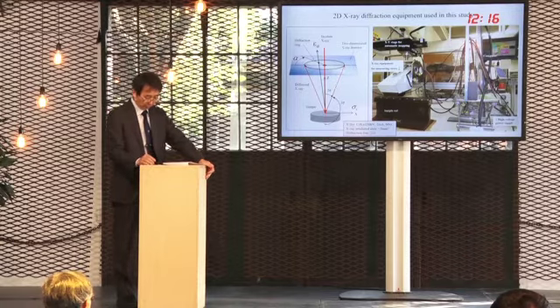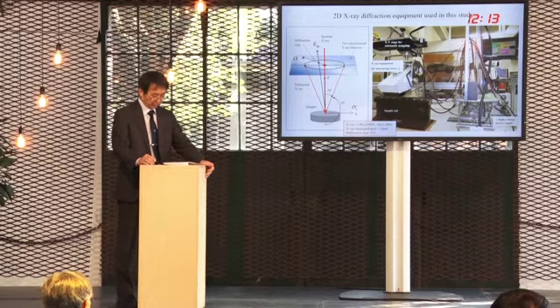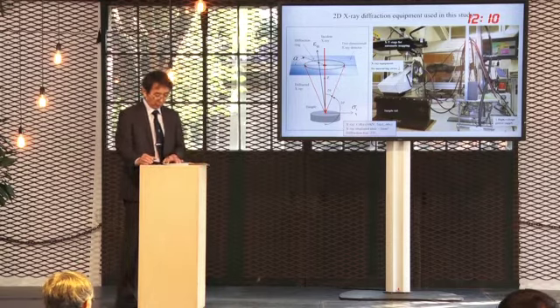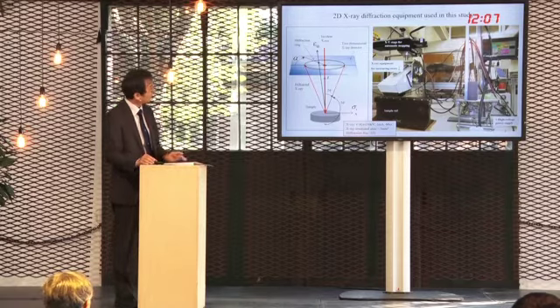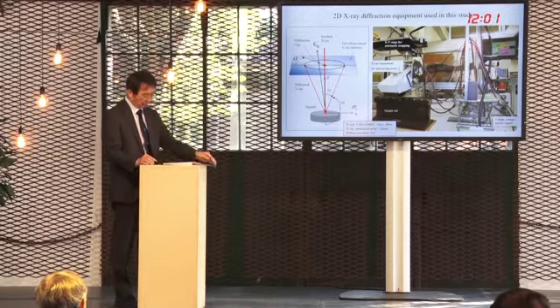The right picture shows the experimental setup used in this study. It consists of X-ray equipment and X-ray stage and a high voltage power supply and a computer. The X-ray equipment was hung from the XY stage to automatically conduct continuous measurement by X-rays. The X-ray measurement time for stress was about 2 minutes per point. This speed is almost 10 times faster than that of the conventional X-ray method.